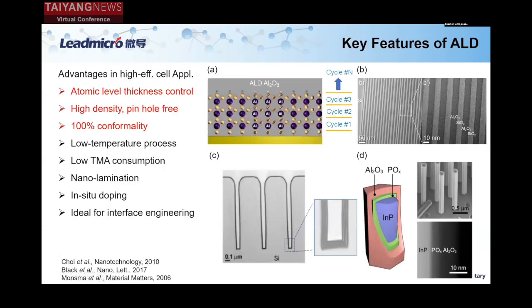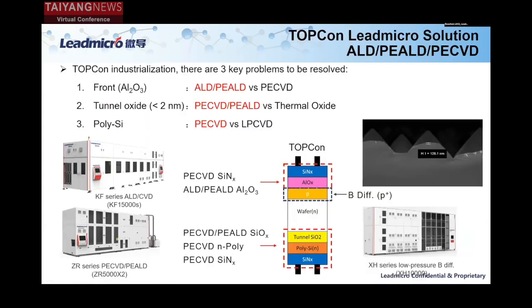So a little bit of the advantage of ALD, as we can see highlighted here. The advantage is atomic layer control, thickness control, high density, pinhole free, and also 100% conformality. So this adds a lot of value when we develop high efficiency cells. If we come back to this page, you can see the tunnel oxide thickness is very, very thin, less than 2 nanometer. How to control this 2 nanometer thickness in sub-nanometer scale proactively? Probably ALD is one of the ideal methods, which we will show the data later.